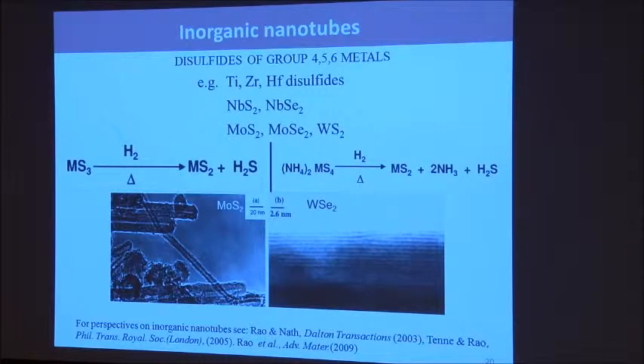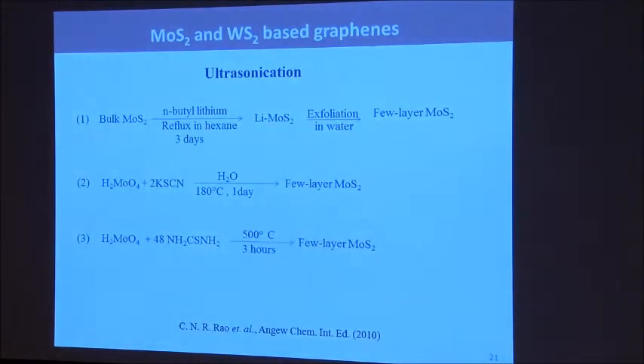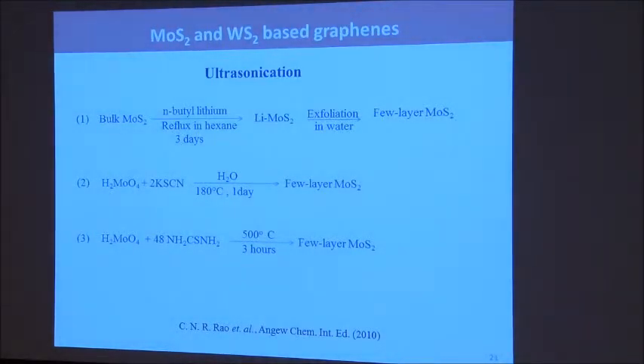So why not make graphene-like material with inorganics? One can make it just like graphene was made, by taking a molybdenum sulfide crystal, using a scotch tape, peeling it off, or by a number of chemical methods—lithium intercalation, exfoliation, hydrothermal methods.